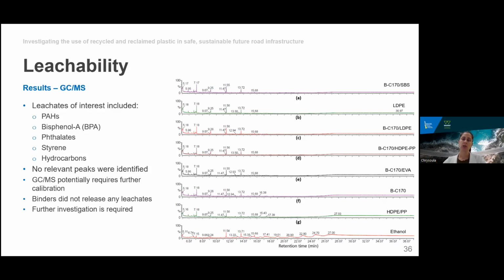We were interested to see whether any peaks for PAHs, bisphenol A, phthalates, styrene, and hydrocarbons could be detected during this process. But as you may be able to see in the results to the right, we did not identify any peaks different to those of ethanol in any of the samples.